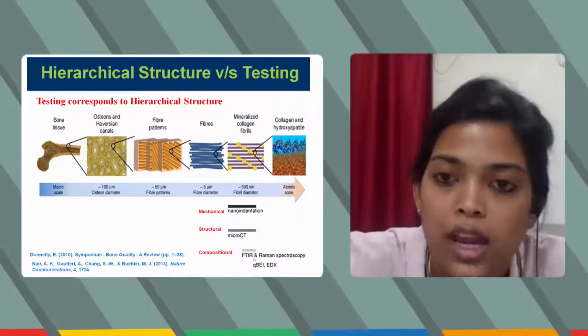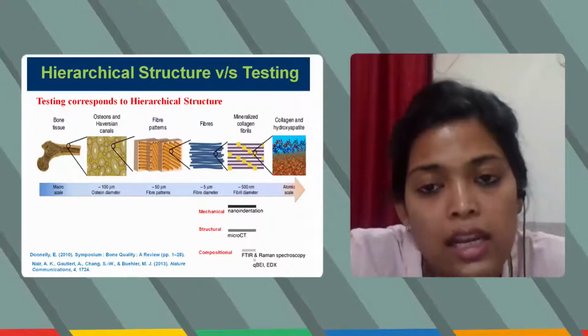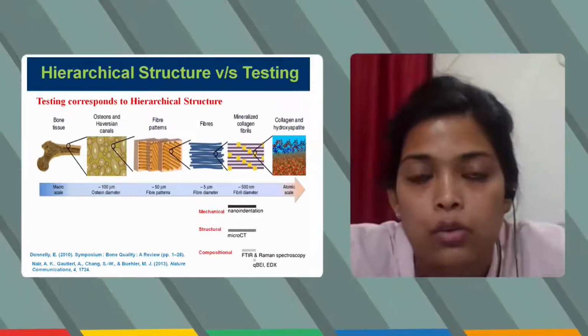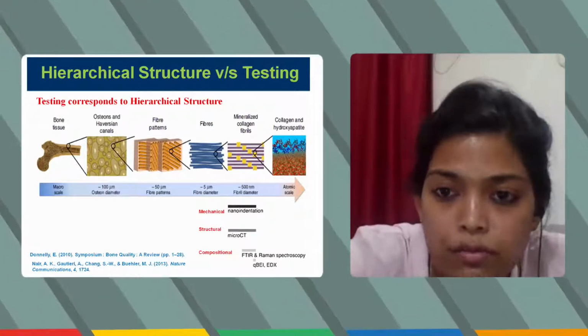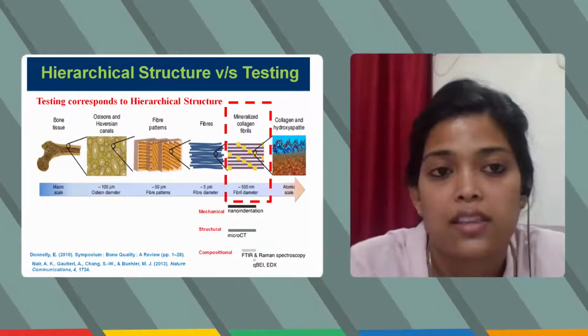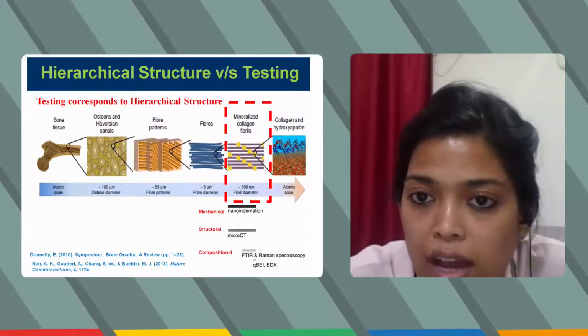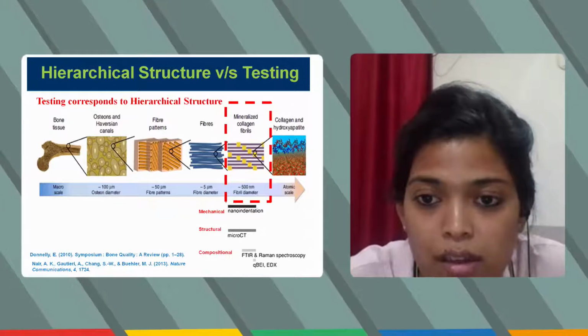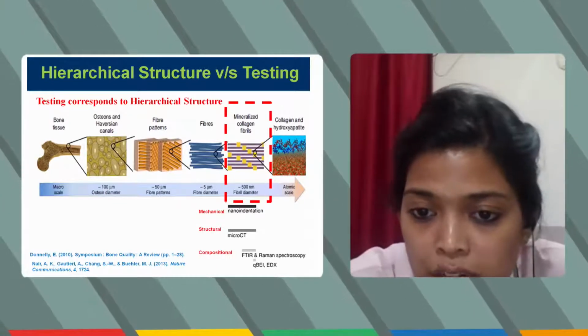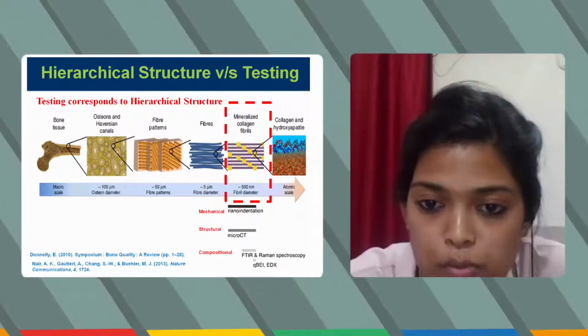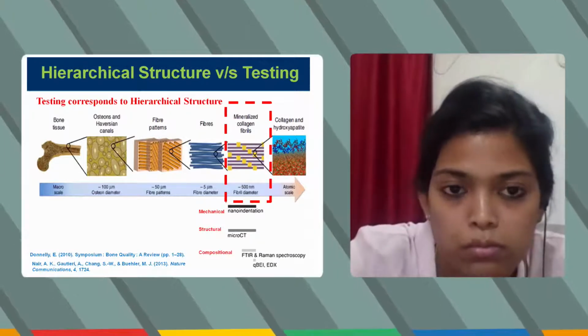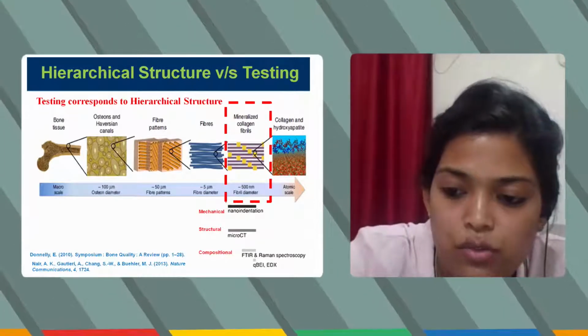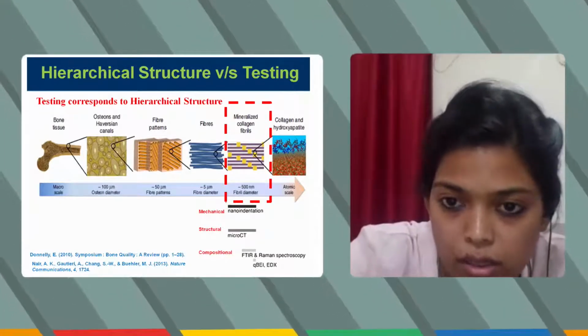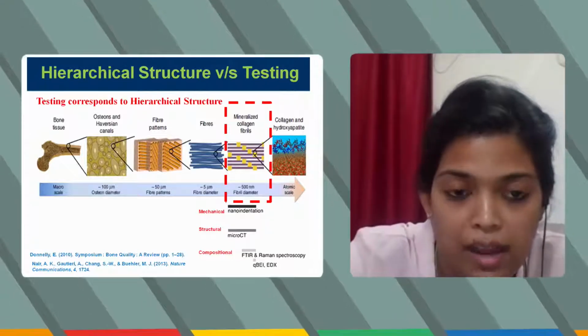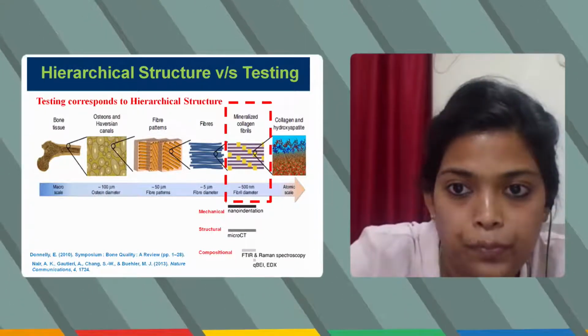So while looking at the bone growing and healing properties, or how the bone is reacting, we must focus at this level, which is mineralized collagen fibrils. And this has to be tested by nano indentation, micro CT, and Raman spectroscopy. So bone is a hierarchical structure which should be tested with different testing parameters on different scales.